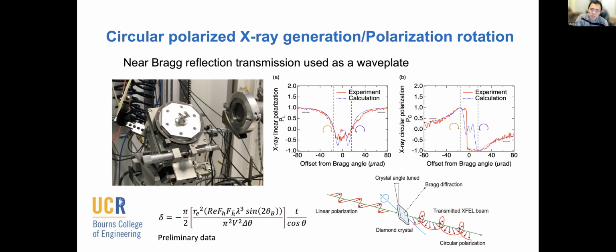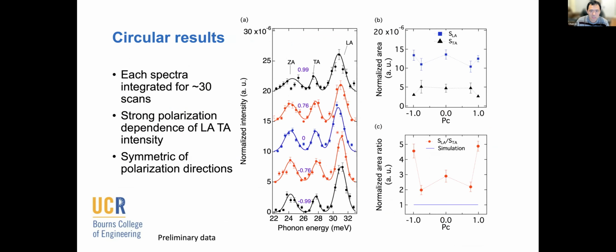So here comes the result if we use this beam to look at our phonons. Here I'm showing five spectra. This is going from 100% left-hand circularly polarized to linearly polarized and to right-hand circularly polarized. By the way, each spectrum actually takes a lot of counting statistics, simply because the beam got so much weaker after the polarizer.